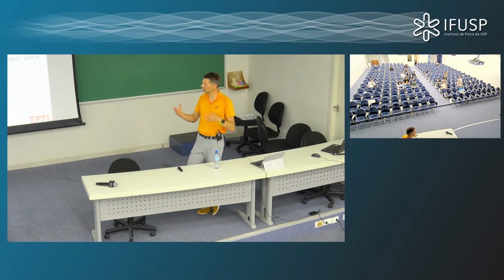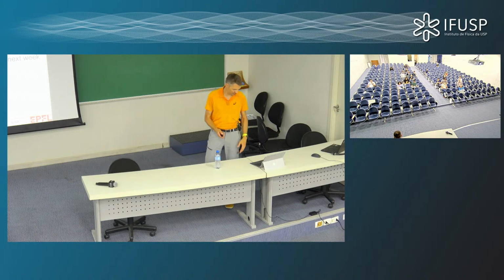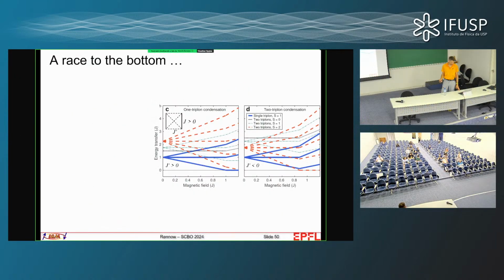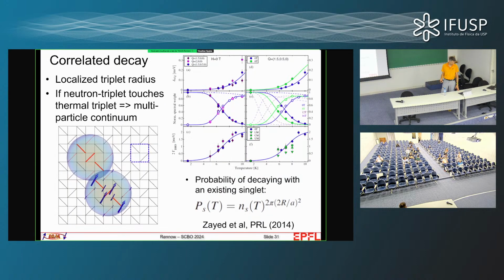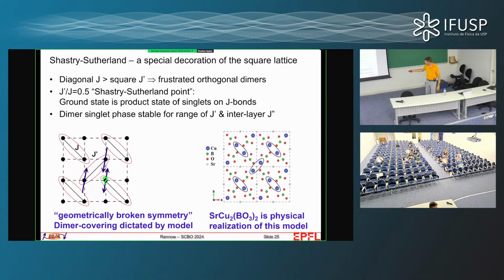But you need a lattice which is topologically equivalent. So notice here, sorry, I need to go all the way back to the start. You can see that in this material, the coppers are not actually sitting in a nice square array, but they sit in a manner that my J prime coupling, which here makes a square lattice, is going in a zigzag pattern like this and like this. And my J coupling here is much shorter. Here it's longer but stronger. And so all you need is a crystal structure where the couplings are topologically equivalent.